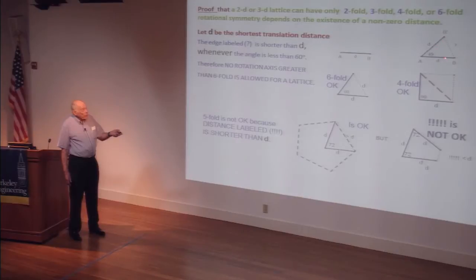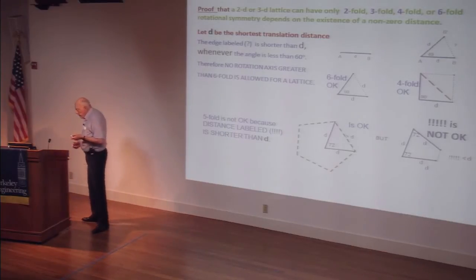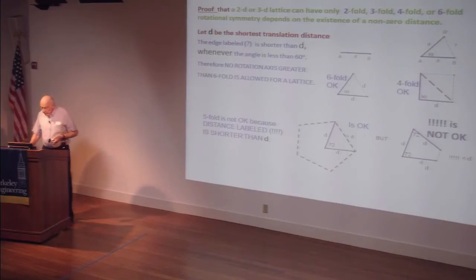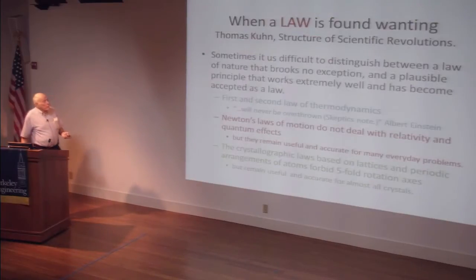No rotation more than 6-fold is possible with a lattice. And here's the 6-fold. That's fine. Nothing new is created. The 4-fold, nothing new is created. The 5-fold, it's bigger than 60 degrees, 72 degrees, and you have that here. But now, if this is a lattice point also, you go 72 degrees to here, and you have something shorter. So 5-fold is not okay. And so that's very, very simple and very obvious. And if you have something periodic, that can't happen.